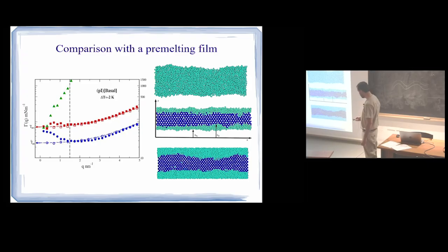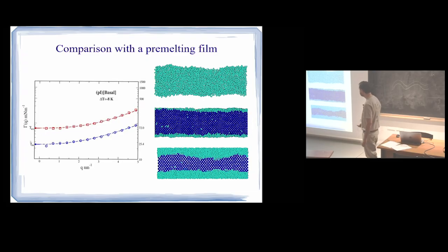Okay? Second, what you can see here is that I am converging to a finite value. Okay? So this prism phase at -2 Kelvin is a rough interface. This is known in experiment. Prism phases, very close to the triple point, are rough. Okay? And here I have plotted also the cross correlations. They all converge. Yes.